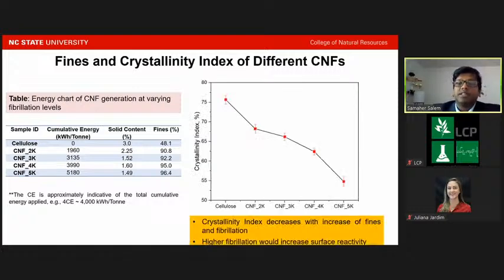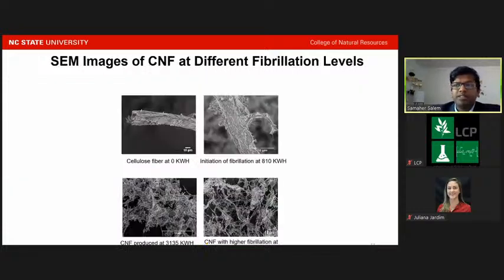And the crystallinity index also shows that with the increase of the energy due to delamination, more and more amorphous regions could be produced, and thus the crystallinity index decreased as we supply more and more energy. This is the SEM image, which shows the delamination resulted in a higher degree of fibrillation. The figure shows that cellulose fiber changes to cellulose nanofibrils as we supply more and more energy.